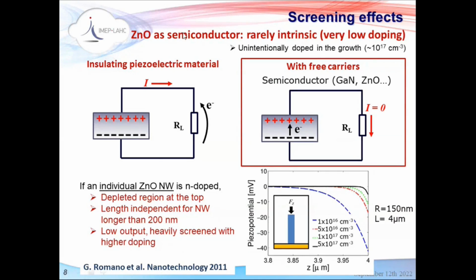Now, the thing is that zinc oxide, so all these nanowires we consider as zinc oxide, is a semiconductor, as I mentioned. So it's actually doped in the fabrication, and it's very highly doped. So that means that we are not in this case, as we simulated before, but actually what will happen is that inside of the material you will have free charges, a lot of charges. So when you deform the material, that you have the polarization, these electrons, for instance, if n-doped, will go and screen this positive piezo potential. So basically you will see nothing outside, and thus you will generate no current. So that is kind of an issue.